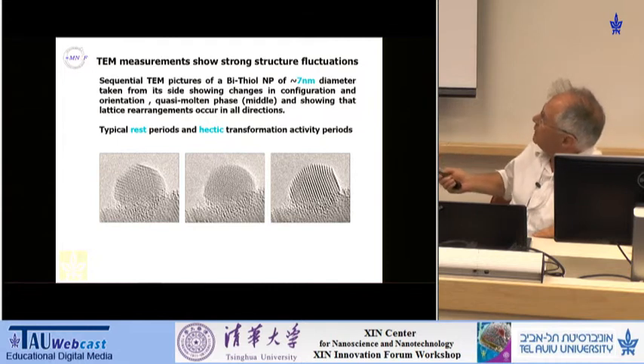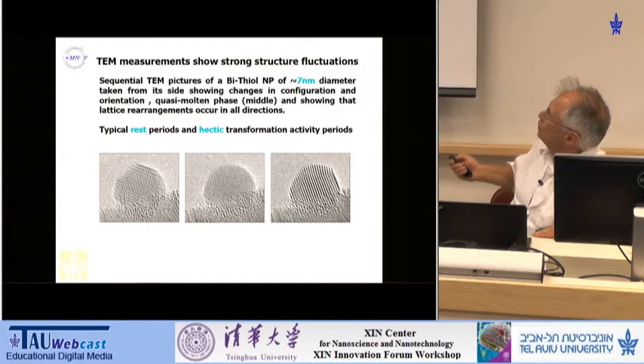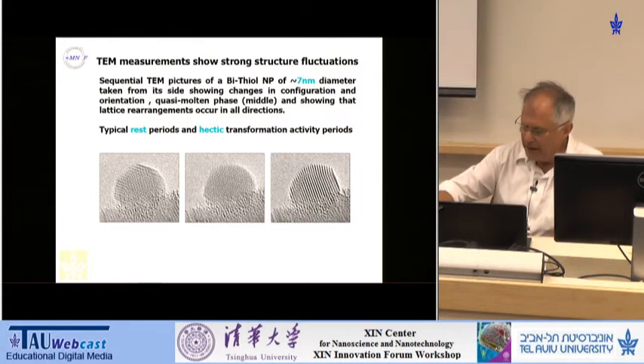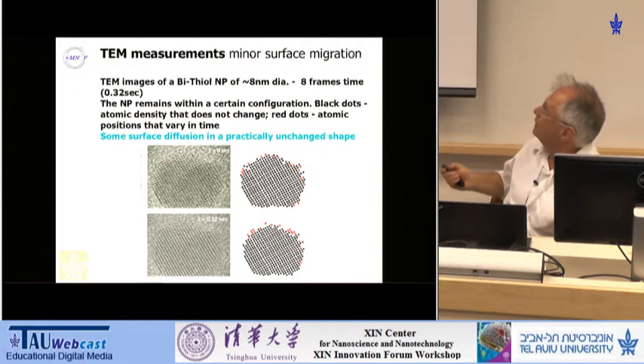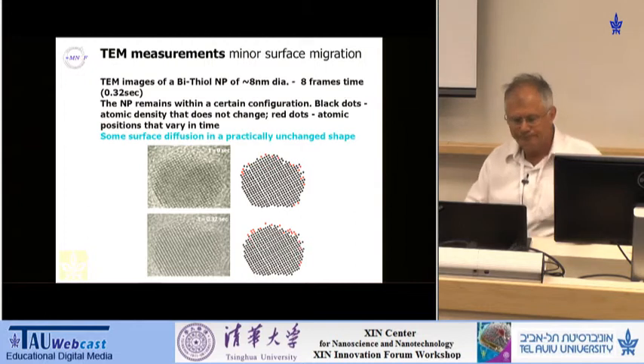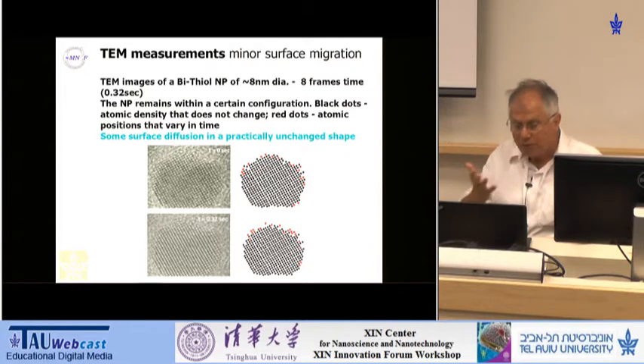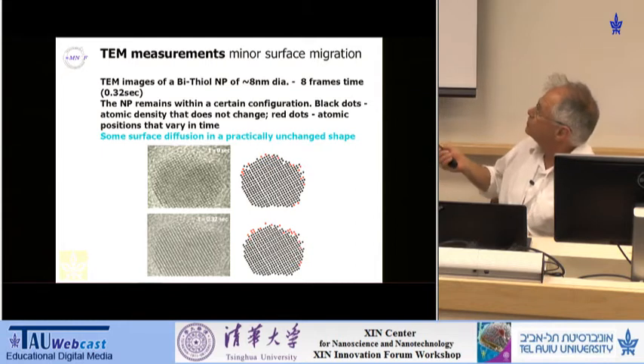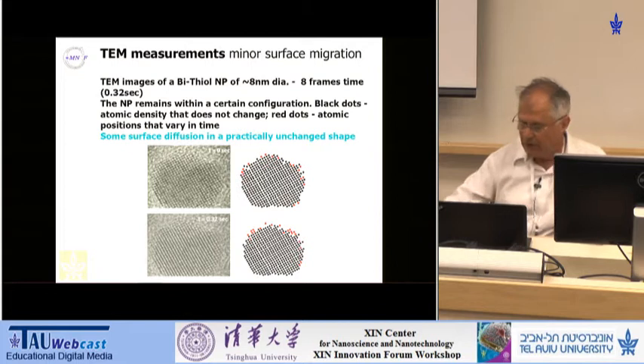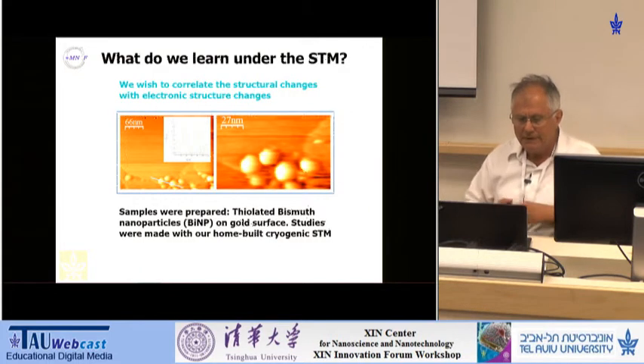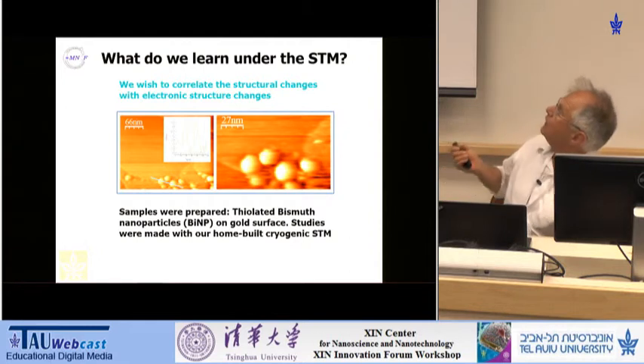This is a picture of the same nanoparticle, those 3 pictures, and in fact they form one shape, and then they sort of melt and form a sphere of melting particle, and then they form another shape. And even in the periods where they are quite restful, don't move, if you really follow the picture, you can see that some atoms on the surface have moved quite a lot. So what we would like to do is to see whether we can learn about the properties of such particles, not only from these pictures, but also by directly measuring properties of such a nanoparticle. And the best tool to do that is to look at this particle under an STM.